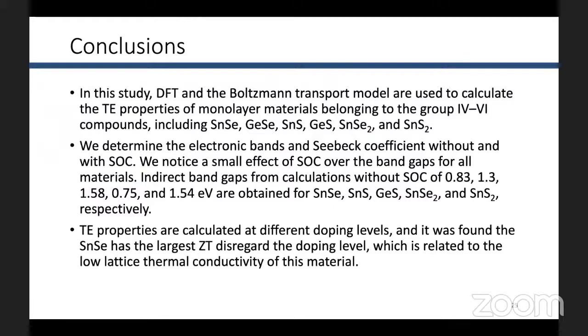And in this study, as conclusions, the DFT and the Boltzmann transport equation model was used to calculate the thermoelectric properties for this list of materials. We determined the electronic bands, which I will not show you in this case, and the Seebeck coefficient, with and without the spin-orbit coupling. And the best material in this case was tin selenide. And this was interesting because tin selenide, I think, was the most studied material in the last 5 or 6 years, with very good results. It's a promising candidate for thermoelectric applications.